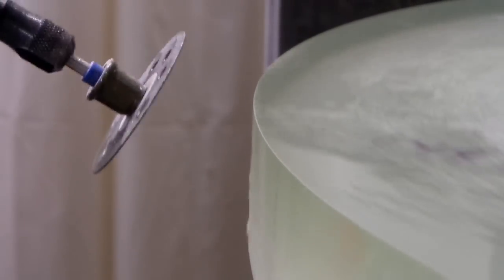I run the rotary tool at full speed and before I start this I wet down the whole edge on this mirror. And then also I actually wet down the grinding wheel itself, the diamonds. And basically, you just hold this up there by hand at about a 45 degree angle and do the bevel. It's real simple.